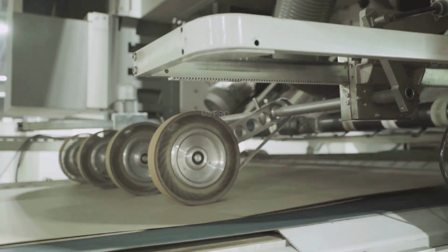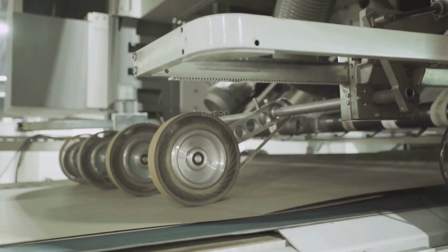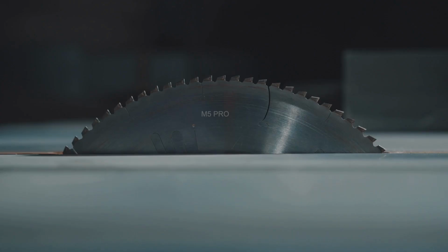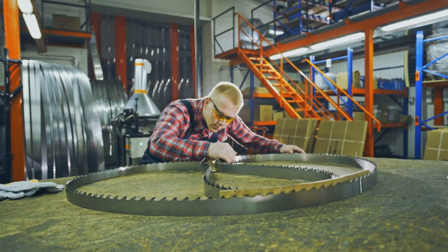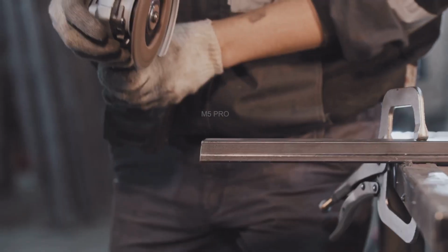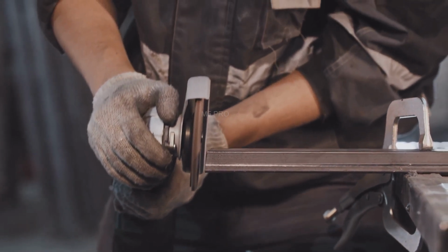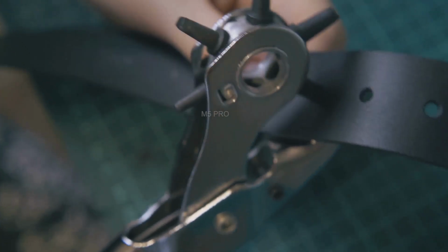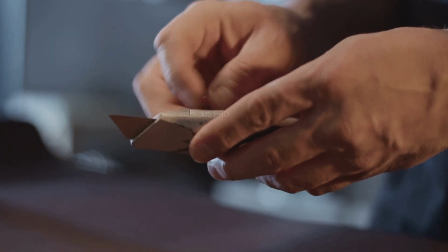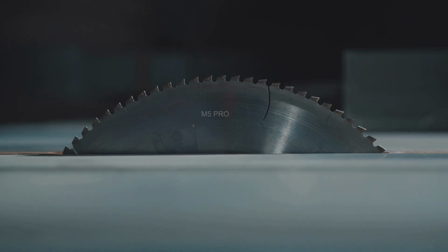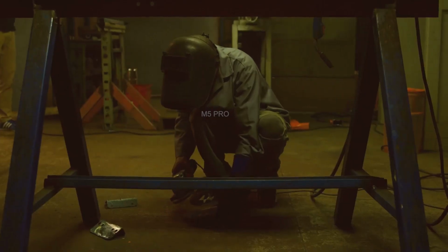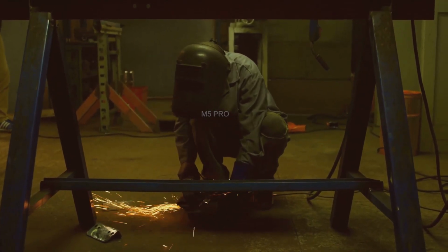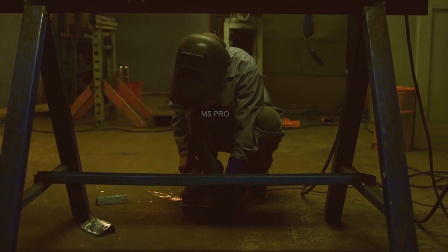This next stage uses progressively finer abrasive belts. We are no longer removing large amounts of steel. We are smoothing the surface, erasing the deep scratches left by the rough grind, preparing the blade for its final finish. An operator takes the blade back to the grinders. The belts now have a much finer grit, requiring a steady hand and a keen eye to maintain flat planes and crisp lines. Each pass on a new belt removes the scratch pattern from the previous, coarser belt. This is a methodical process of refinement.